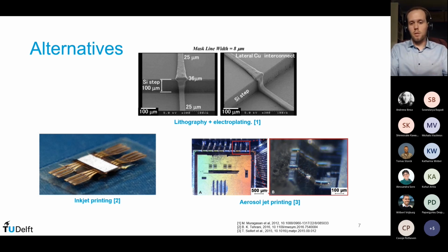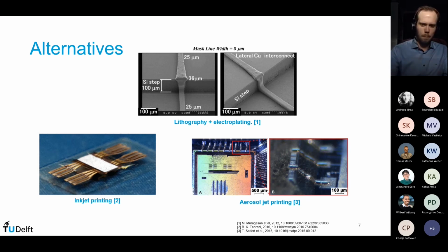But you still have the downside that you need an ink. And ink formulation is challenging. There's a limited shelf life of it. You have a problem that you also have always a curing process. So you will need to heat the sample, or at least let it dry and rest for a while before you get a reliable connection. Even then, you'll have organic pollutants in your line, which will probably reduce performance.